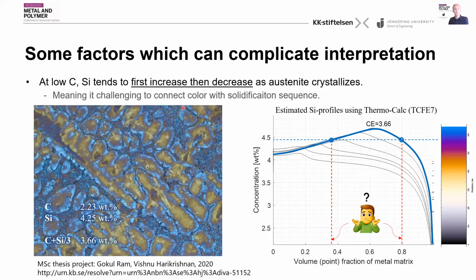Here on the left, you see a color-etched micrograph where this is emphasized. This is a material where we have a quite low carbon equivalent and at the same time high silicon content. And in this case, we actually saw that instead of the core of the dendrites being rich in silicon, they are actually impoverished in silicon, have a lower concentration. And then the outer parts of the dendrites, which formed later in the solidification sequence, actually have higher concentration of silicon.